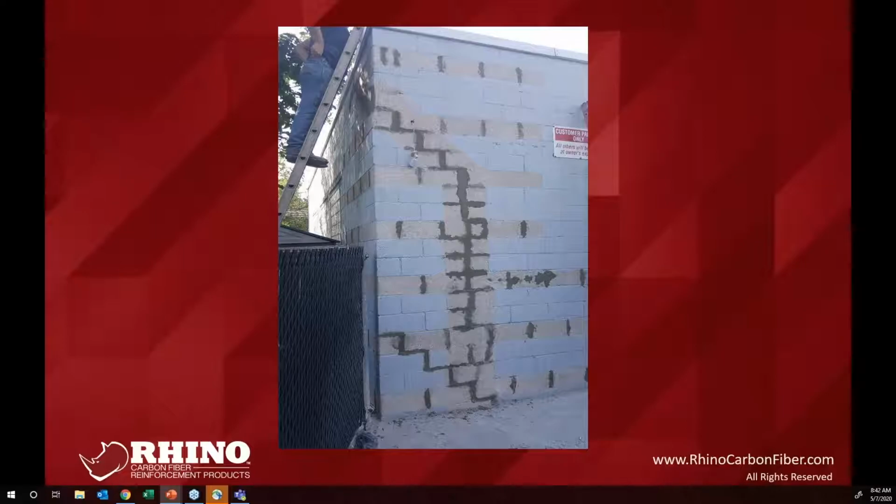Since you have surface preparation error, then what you're really looking at is that surface preparation has caused a failure in the epoxy. The largest contributor to that for a long time was that you failed to open the pores of the concrete so it doesn't have an adequate bonding surface. What I recommend in that particular case is always use a vacuum to suck all the dirt and debris that you've ground off out of these pores and open them up.